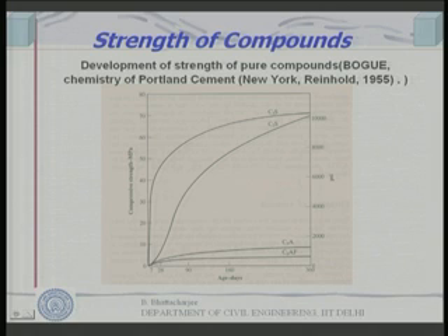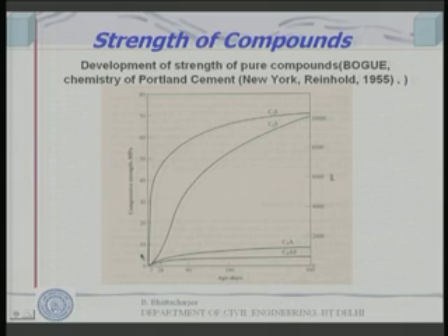So, it is the C3S which gives me early strength, but later on you can see as the age increases this strength does not increase, it is nearly becoming flat. Whereas, if you look at C2S on the other hand, initially the strength growth is not so much, but it tends to give you long term strength.